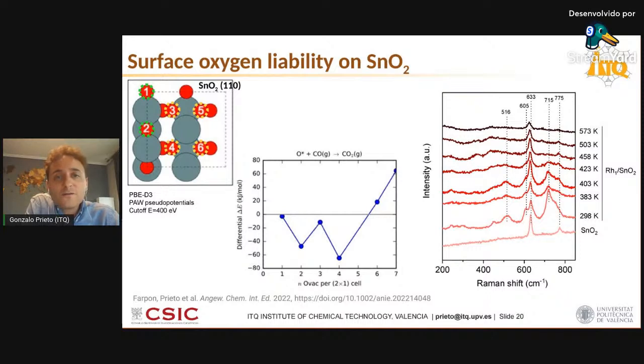Why? Because tin oxide is one of the preferred oxides in the area of sensing light molecules. And there, the oxygen chemistry of the surface of tin oxide plays an essential role. So we decided to go for a complementary theoretical and experimental study on this oxygen surface chemistry. On the computational side, we use periodic DFT modeling. That's in cooperation with our colleagues in KIT, Felix Studt and Philipp Pleßow, already long cooperations from back in the times where I was based in Germany. And we concentrated on this 110 tin oxide surface, which is the most stable and therefore the one which is predominantly exposed on the relatively low surface area of catalyst that we are dealing with.